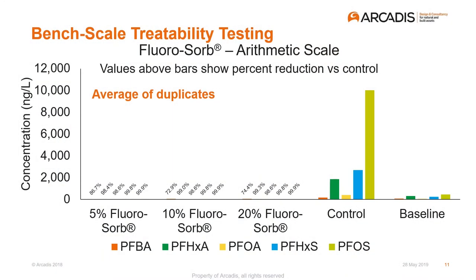Concentration on the y-axis here is parts per trillion, nanograms per liter. So primarily PFOS dominated, up around 10 parts per billion. Again, liquid phase concentrations. And then 5, 10, and 20% by weight FLUORO-SORB doses showed anywhere from 75 to 99.9% removal. So really, really, really good data.